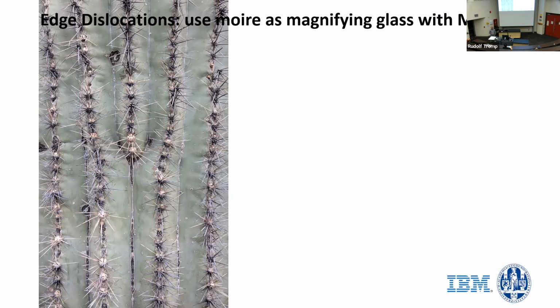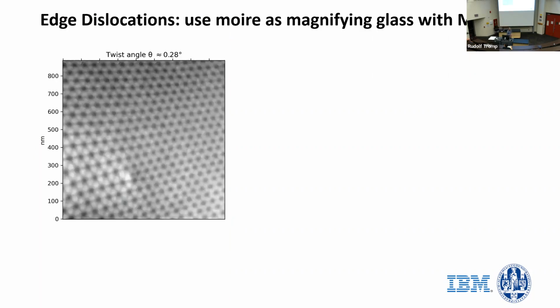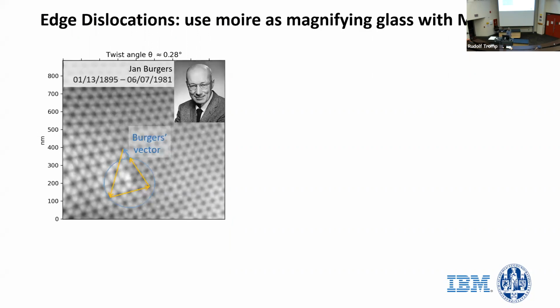Dislocations are small, right? They have a core that is on the order of a few angstroms or so, and we don't have enough resolution to see those, but it turns out that we can use this Moiré lattice as a magnifying glass for the dislocations. So let me show that to you. Here's a dislocation. If you follow this line here, it ends at a twist angle of 0.28 degrees between the top and bottom layer of graphene.